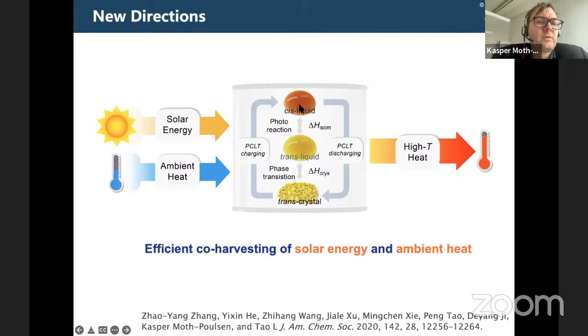But there are two things happening. One is the photoconversion that is storing chemical energy, but the other one is the phase change. And to melt this, you absorb heat from the surroundings. So you basically take in both solar energy and ambient heat to form the liquid state. Then when you isomerize back from the liquid, you transform and crystallize. You get both the isomerization energy and the crystallization energy. So in this way, you increase the total stored energy, and you also have an interesting phase change behavior. So altogether, it creates a large amount of energy stored. But moreover, it's also two different mechanisms.